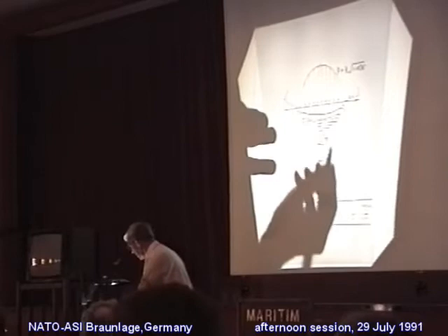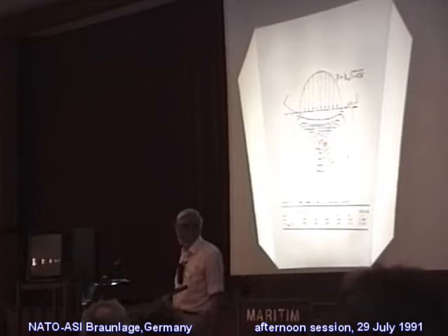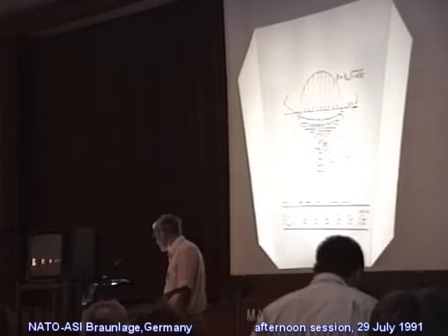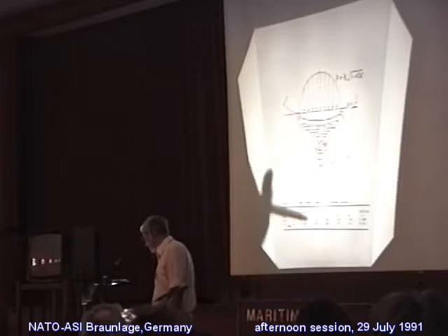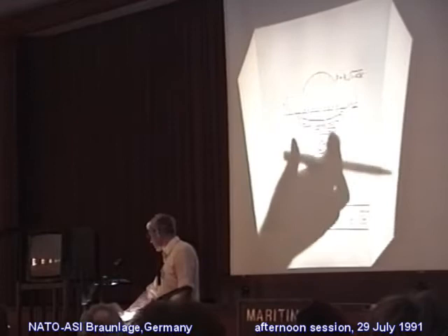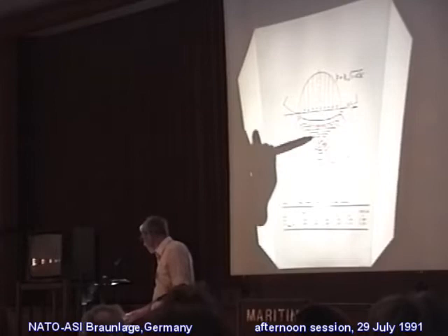Well, something like a volume here that we yield first is fully contained by surrounding elastic material, so that the plastic strains must be of the same order as the elastic strains. And in fact, it's very difficult to actually know that yielding has occurred. We can say in logic that if you get some plastic deformation here, which will comprise compression perpendicular to the surface and extension parallel to it, that will be accompanied by a small permanent deformation in the surface. But this volume is small, and it needs very refined instrumentation to detect that in the surface.